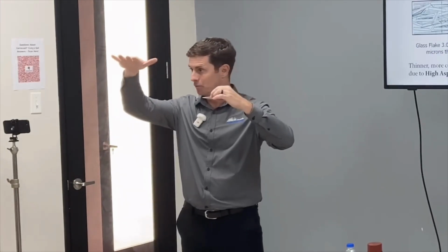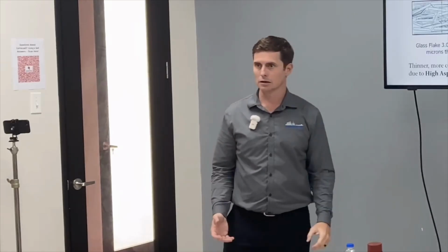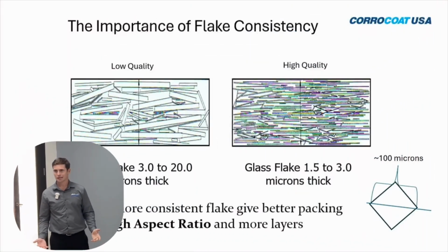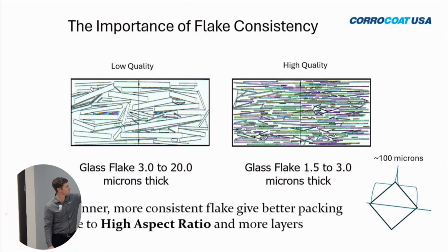Whereas if you have a perpendicular force on a high aspect ratio glass flake or anything that's flat, like a piece of paper, for instance, it's going to want to stay flat and parallel to the substrate. This is really, really important when you're looking at barrier properties to glass flake coatings. When you use lesser glass flakes, those glass flakes have a chance to wick, and then they're just not going to give you the same tortuous path.